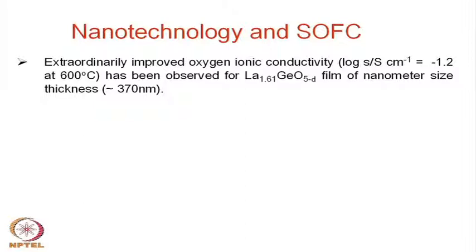Extraordinarily improved oxygen ion conductivity, this is log sigma of the order of minus 1.2 at 600 degrees, has been observed with lanthanum germanate film. This is not YSZ, of course, this is not YSZ.